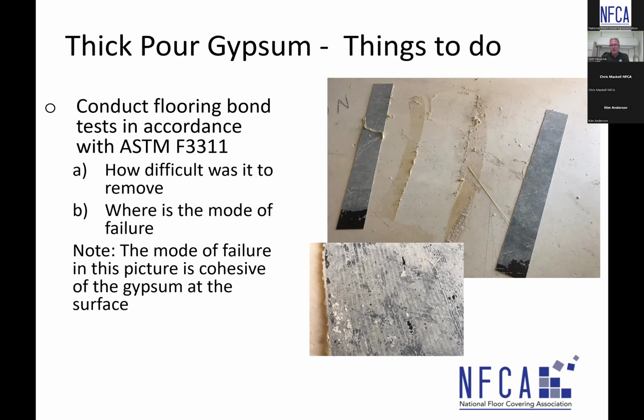Basically, what you're doing here is you're taking a 2x2 piece of flooring and you're adhering it, preparing the substrate, whatever it might be, combing out adhesive in accordance with manufacturer's recommendations, appropriate open time in accordance with manufacturer's recommendations, dropping the flooring in, rolling it with a 100-pound roller, taping the entire perimeter, letting it go for at least 72 hours, and then you come back and you cut a 2-inch strip.